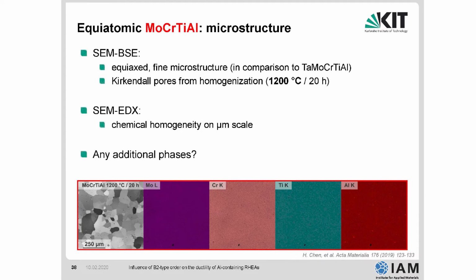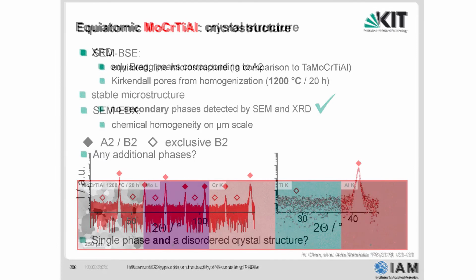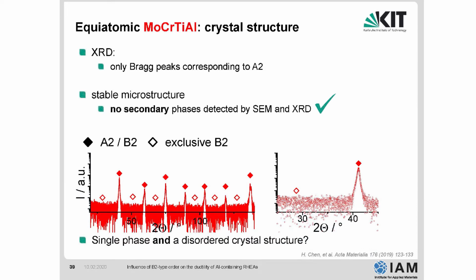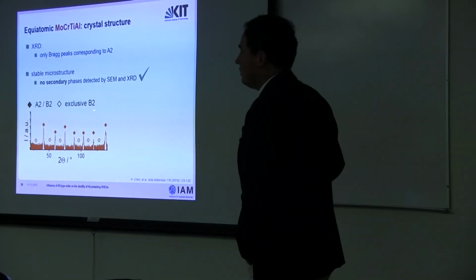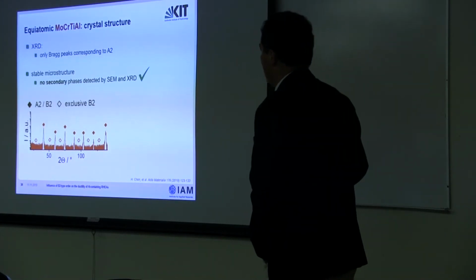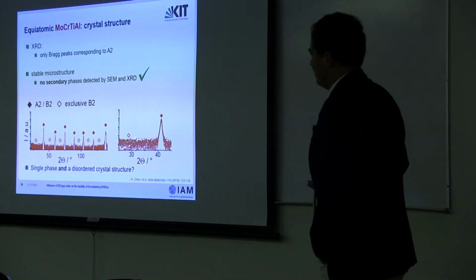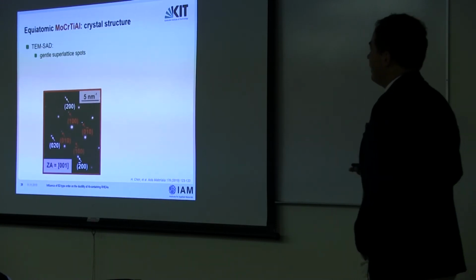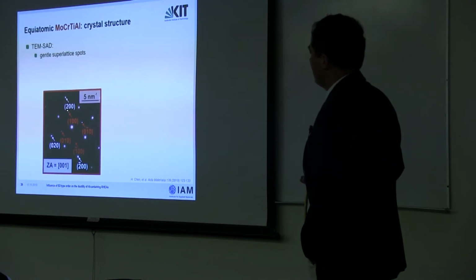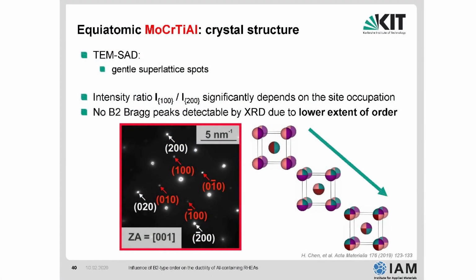So we started first with taking out the tantalum completely. No tantalum should mean no Laves phase, right? Because chromium-2 tantalum is the Laves phase. Again, this alloy is single phase. Again, we have some tiny ordering superlattice reflections, but much less than in the other case. You can hardly see the superlattice reflection spots. There's not much left here in a magnified view. But in TEM you can see it. This is a TEM selected area diffraction micrograph. You see gentle, really not very prominent superlattice spots.